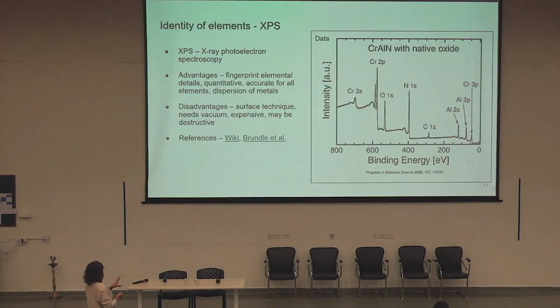So this is the working principle of XPS, and the advantage is that it is quite accurate. It is going to tell you surface versus bulk composition. The disadvantage is that it is very expensive. Whenever you need to create a vacuum, you increase the cost of the equipment because you are putting in additional things like pumps to maintain that vacuum. It might also be destructive when you are ejecting electrons out of the sample, for many samples, depending on the conductive nature of the sample. And sometimes the sample preparation can be difficult, but it is not as difficult when compared to, say, your TEM.